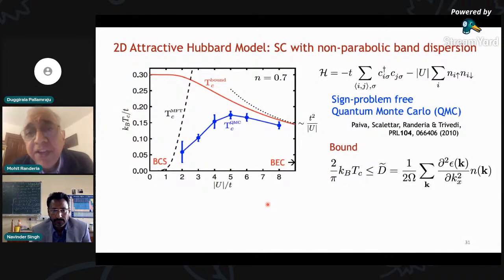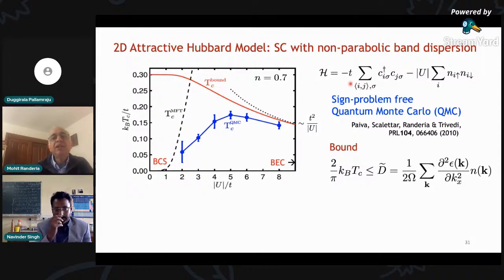So now let's look at non-parabolic band dispersions, because the parabolic band dispersion is very, very special. So what to do? The simplest thing you can do is to write down the simplest lattice model with nearest neighbor tight binding on a lattice with attraction, the attractive Hubbard model, different from the usual Hubbard model, which gives you S-wave superconductivity. And here you have the luxury of being able to do sign problem-free quantum Monte Carlo that I did with several Monte Carlo experts more than 10 years ago now.